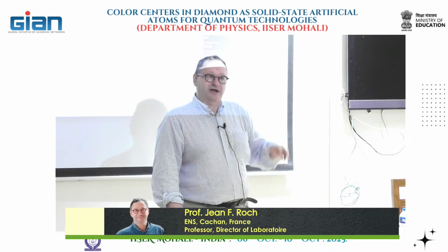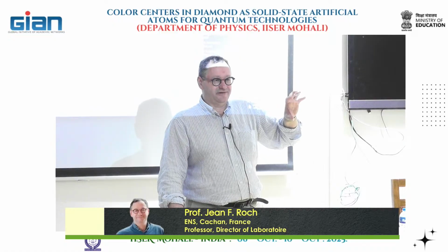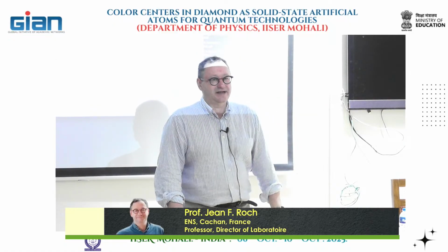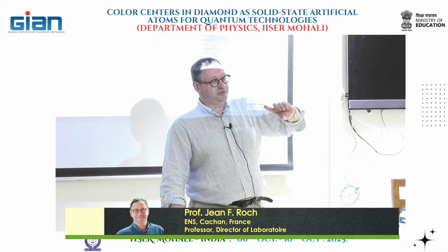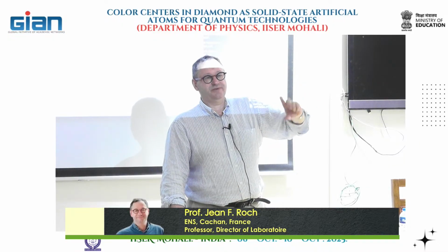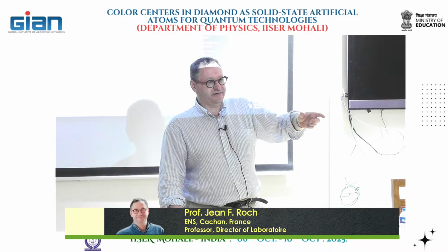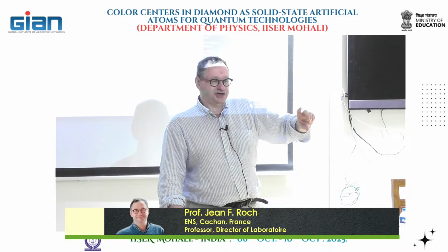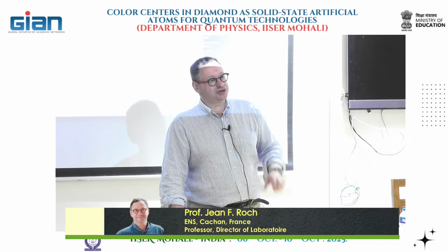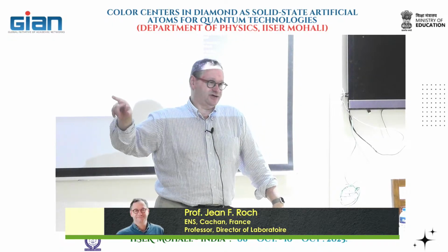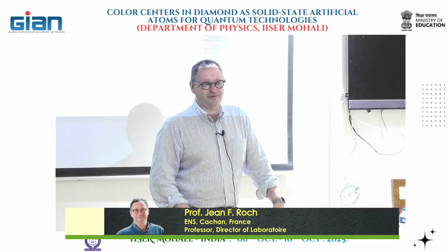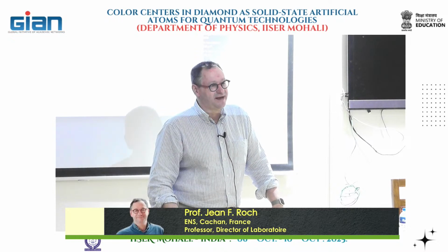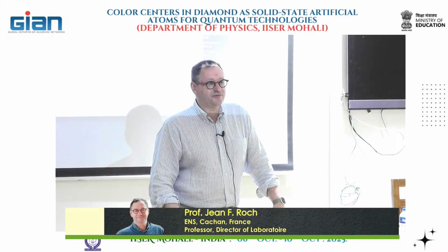The other possibility is to start from a real single atom source, and people know how to do that. For instance, we know how to trap a single ion. Usually it's calcium or those kinds of ions. And then with some exchange, you're able to trap one nitrogen, and then you shoot the nitrogen. Because you know that there is only one ion in the trap from the very beginning, you know that you will get only one ion at the end. So this is very nice also.